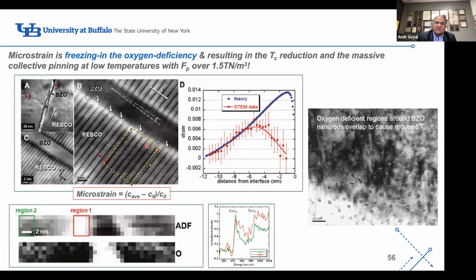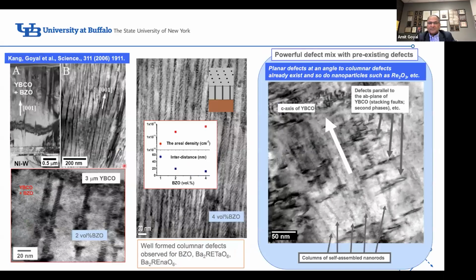It peaks somewhere close to the interface, and because of this high density of point defects, we get beautiful pinning at low temperatures. And so we can control the number of nanocolumns, we can control their areal density, and this is now a well-used technology to make the highest performance superconducting wires in long lengths.